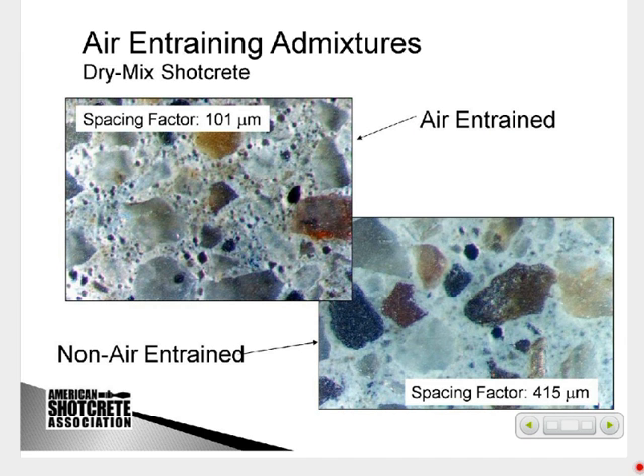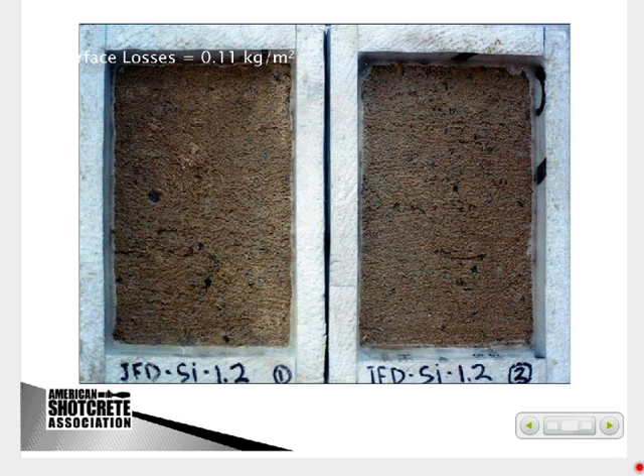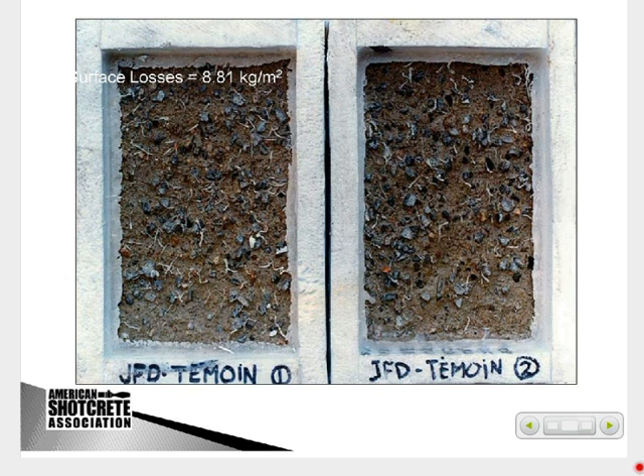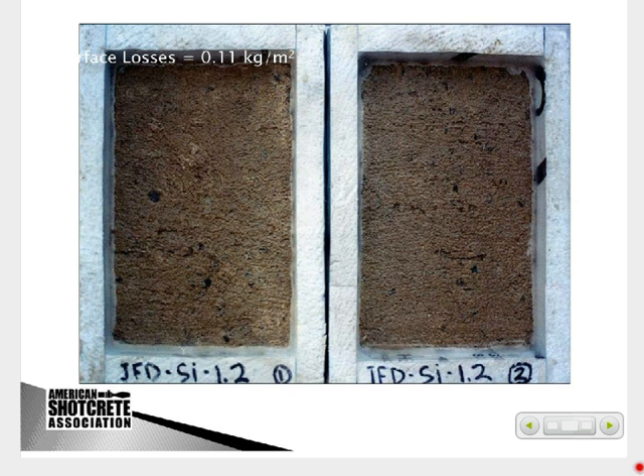We can add air entraining. Certainly wet mix, you get your concrete delivered with air entraining. One thing with shotcrete, as it hits the surface, you will lose air entraining. So if you want to achieve say a 3 to 4% in-place air, you may actually be shooting an 8% material as delivered. Just to give you an idea of air entraining, here's 2 samples that were shot. This is what it looks like when it didn't have air entraining. This is how it went through the cycles with air entraining.